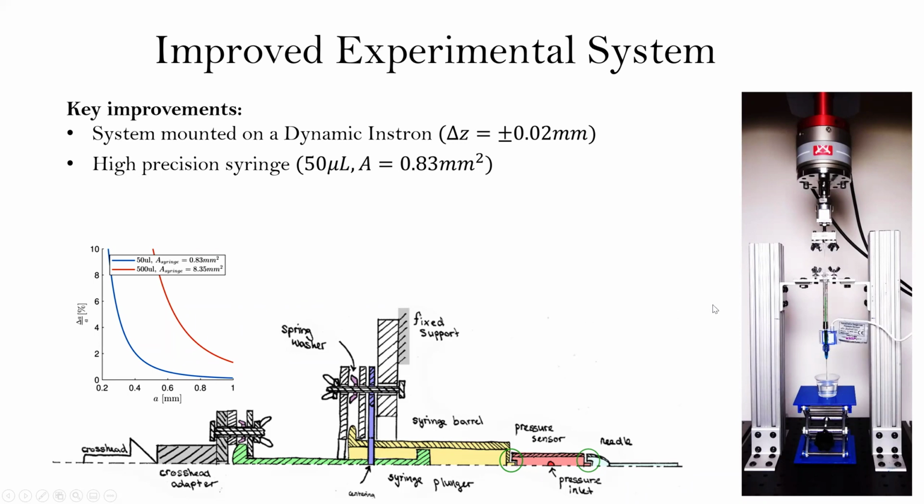And what we see is that when we were typically using 3 ml syringes, which are quite fat, and we go to these gas tight syringes that are extremely thin and have a 50 microliter volume, there's a significant improvement in the volume measurement error and consequently the effective size of the cavity. So that already gives us high precision for the measurement of the cavity size.